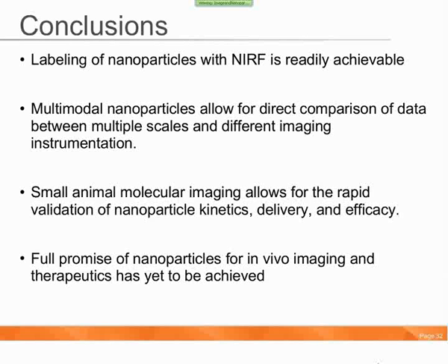And finally, I feel like really the full promise of nanoparticles for in vivo imaging and therapeutics has yet to be achieved. A lot of this work has been done on delivering nanoparticles to tumors where you have competing forces, including your targeting moiety, enhanced permeability and retention, and increased turgor pressure in the center of tumors. Nanoparticles may be more effective at areas that are much better perfused and don't have that increase in turgor pressure. So I think there's a lot of opportunity for you in in vivo imaging to rapidly validate when nanoparticles can be effective and when they're going to be specific.